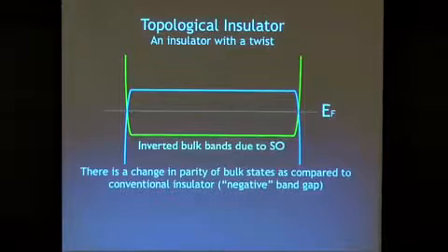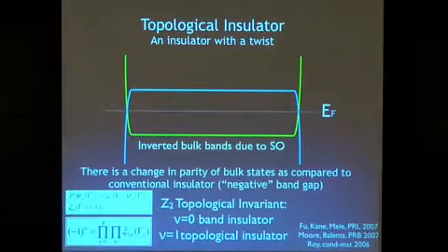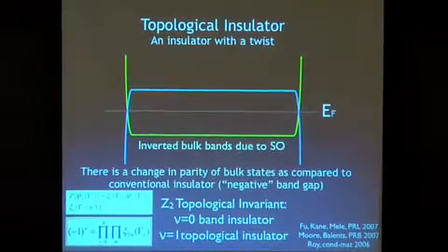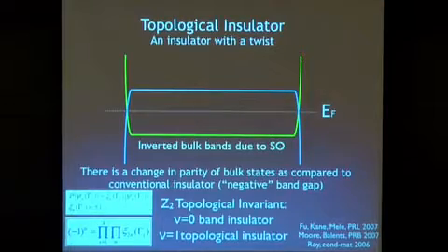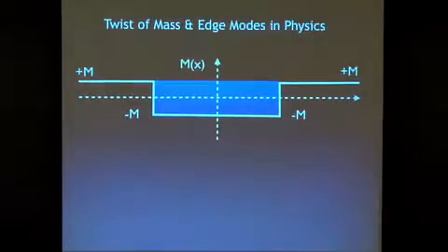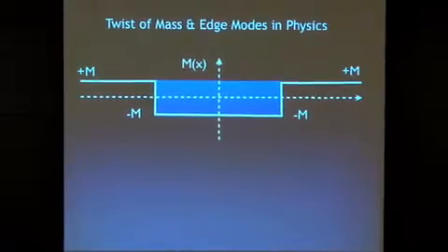You have changed the order in which electronic states appear from that of the atomic limit, and you have done this in a way that you can also determine if you went to the band structure of this material and looked at the parity of the electronic wave function. A whole host of theorists have shown us how you can determine whether an insulator is of the topological type or of the trivial type. Now, what's interesting about this twist is, of course, that it can't be undone. You can think of that twist also as the energy gap associated with the semiconductor having changed sign. Inside the material you have an energy gap of one sign, and outside you have an energy gap of a different sign.